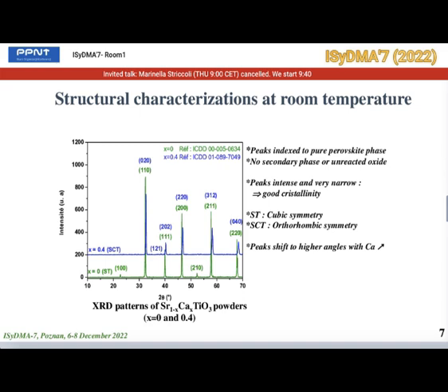Here we have the XRD patterns of the ST and SCT powders at room temperature. All the peaks of the XRD diagrams were indexed to the pure perovskite phase. The peaks are intense and very narrow, showing a good crystallinity of the samples. ST material shows a cubic symmetry. For SCT material, the observed peaks are characteristic of an orthorhombic phase or structure. All peaks shift to higher angles 2 theta with increase in calcium rate in SrTiO3 material. This is due to the fact that the ionic radius of Ca2+ is smaller than that of Sr2+.